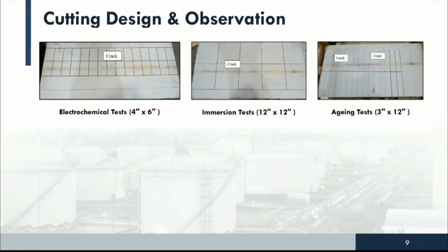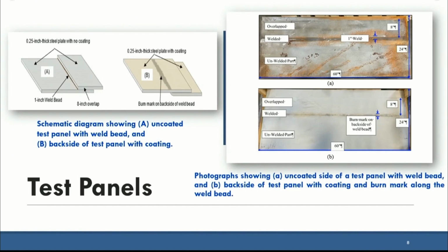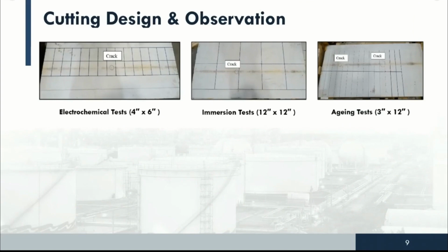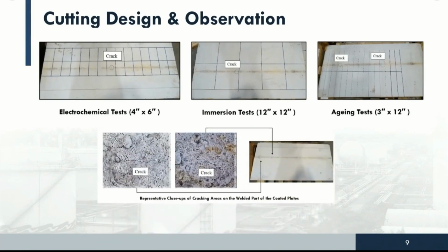Oh, sorry. Shall I go back? Okay. The green. This is the back side of the panel that is going to face the internal of the tank, whereby here is the coated side that is going to face the soil side of the tank. As received panel with the coating, we find that on the welded area, there is discoloration. And we said, okay, fine. Then we started cutting the panels for the immersion test, for the electrochemistry, and for the aging. And we have observed that there is also some cracking and some disbondment after we cut the panels. We selected panels that did not have any of these because we created our own damages to it.